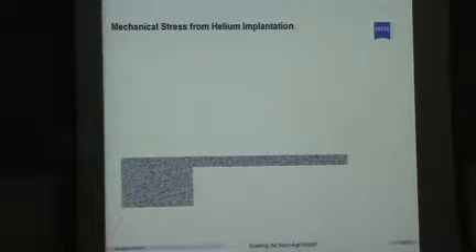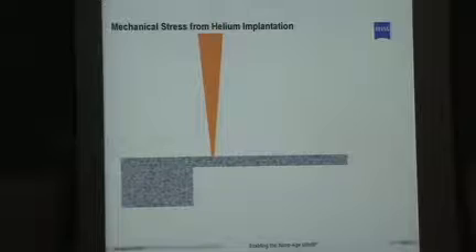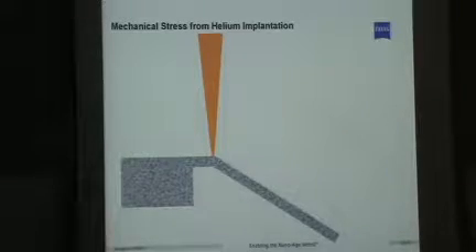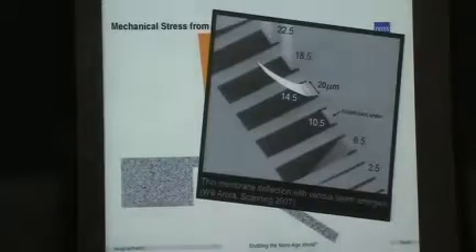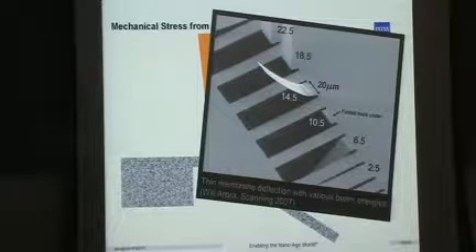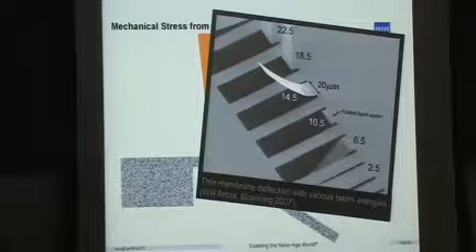One of the other things, our collaborators who are right in our same neighborhood at MIT were interested in membrane folding, and they were using gallium to induce stress by breaking polymer bonds and such. And they wanted to put a beam down and see something bend. Well, it turned out we were terrific at that. And in fact, with gallium, it always points down. With helium, we can make it point up.